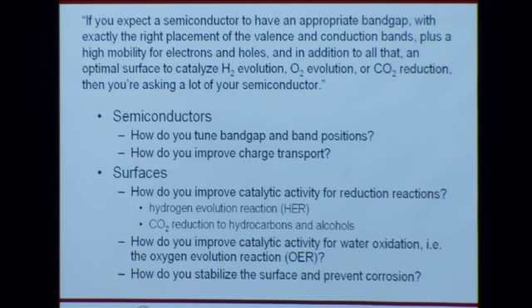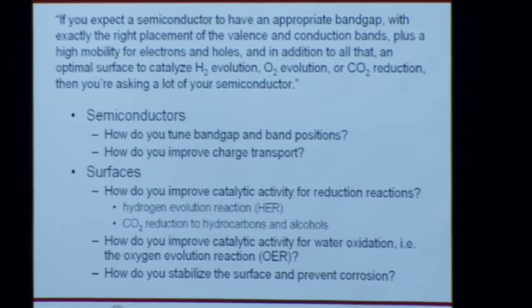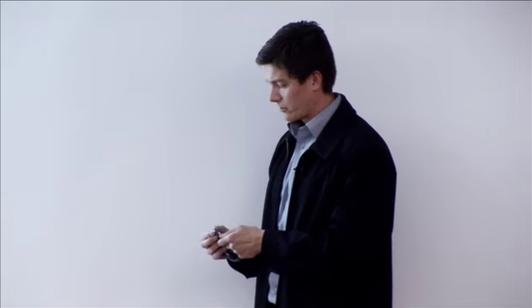Okay, so a lot of research in this area has really been predicated on the thought of creating a semiconductor that can in fact satisfy all of these requirements simultaneously. But in our lab, what we're doing effectively is dissecting the problem. And I'll tell you why, because I believe very firmly in this statement. I'm happy to be proven otherwise, but I'm going to read this out to you. If you expect a semiconductor to have an appropriate bandgap with exactly the right placement of the valence and conduction bands, plus a high mobility for electrons and holes, and in addition to all that, an optimal surface to catalyze hydrogen evolution, oxygen evolution, or CO2 reduction, then you're asking a lot of your semiconductor. Okay, there's no physical reason why such a material couldn't exist, but what we're going to do is dissect this problem into really 2 general areas, that of semiconductors and that of surfaces, and we're going to try to develop these types of materials independently and then interface them together to make a device.